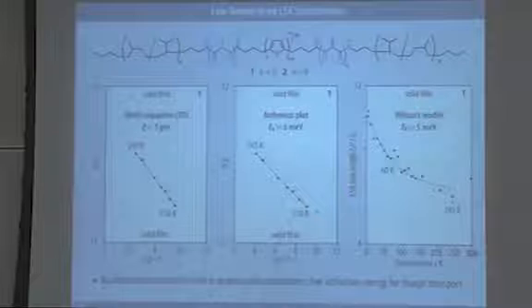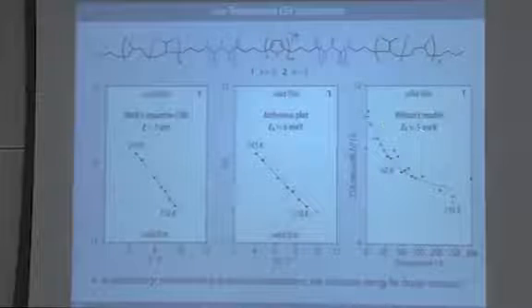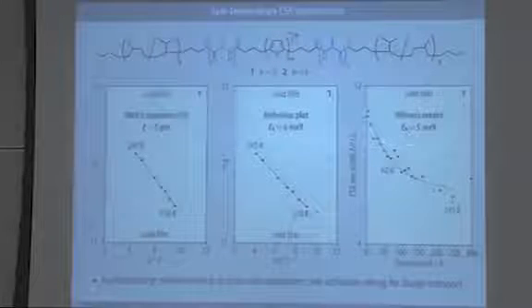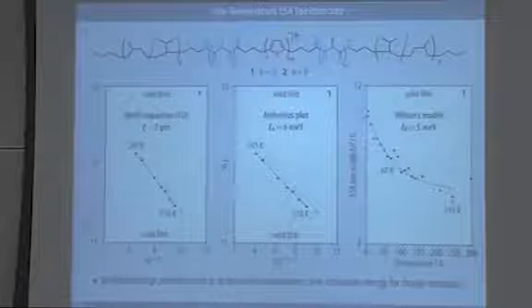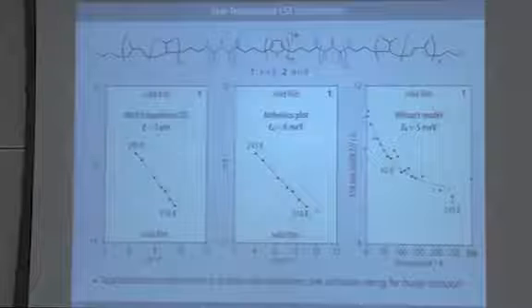The parameters we obtain, you obtain different time frames out of this data, actually fit to the data reported in the literature. But again, we have a very low activation energy that coincides pretty well with the activation energy we observe from the paramagnetic susceptibility data. So that is where we are.